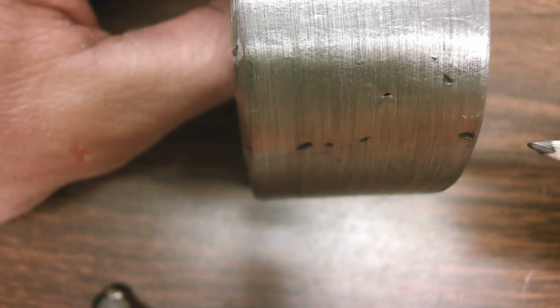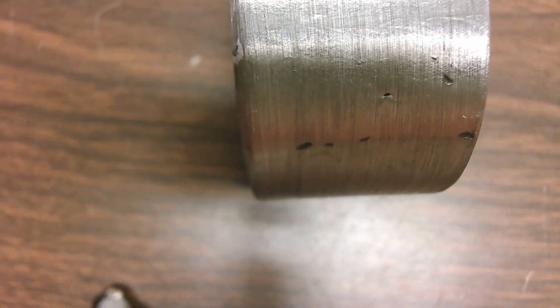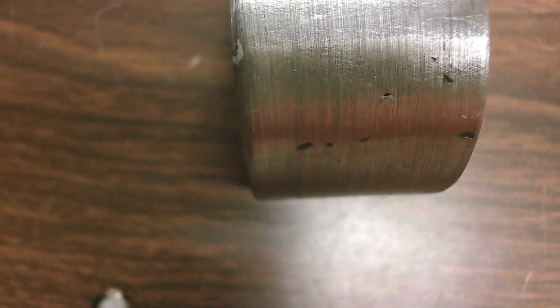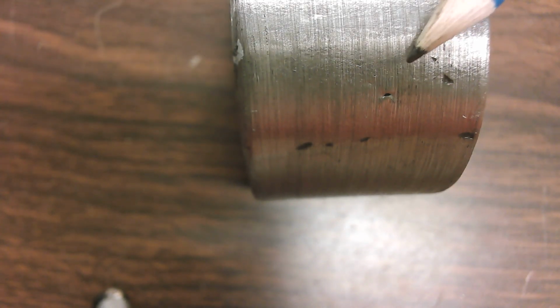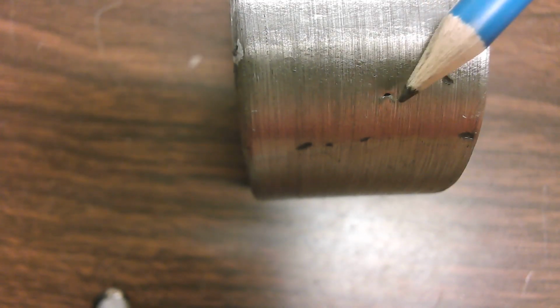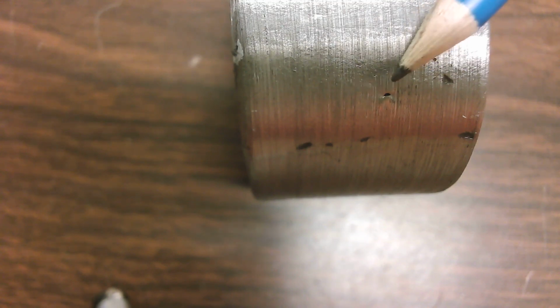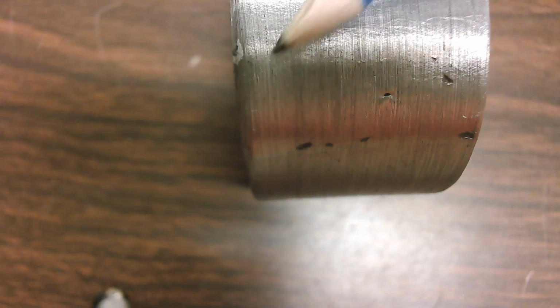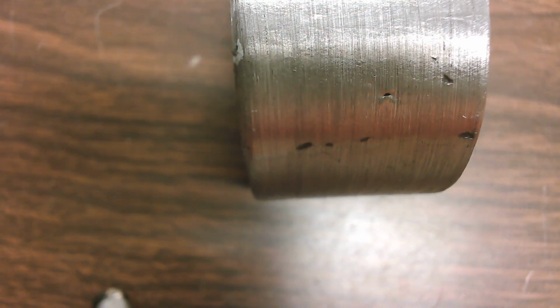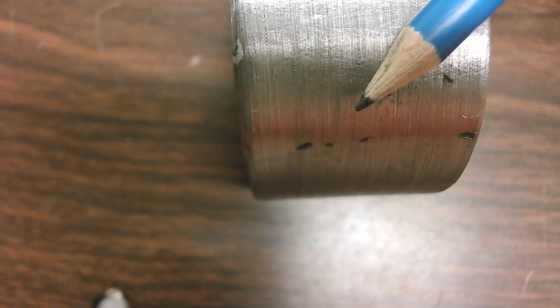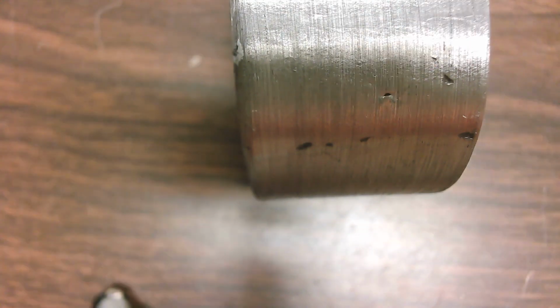If it's more than a 32nd of an inch but less than 1/8, then we would add up the total. Well, in this case, there's only one. So regardless whether it's a 32nd of an inch or just over a 32nd, it's clearly less than 1/8 of an inch long, okay? And there's not multiple ones, so we don't need to add up anything. So this face bend would pass, okay?